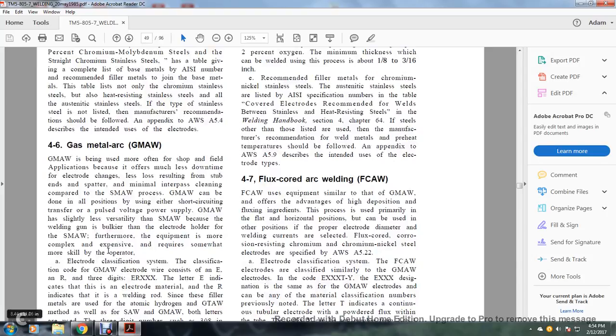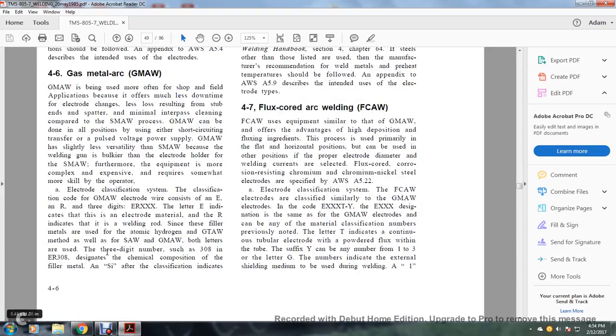Gas metal arc welding, 4.6. Gas metal arc welding is being used often in the shop and in the field, with less downtime for electrode changes, less loss from electrode stub ends, and minimum spatter and interpass cleaning compared with the shielded metal arc welding process. Gas metal arc welding can be done using short circuiting transfer or pulsed voltage power supply. It is slightly less versatile than shielded metal arc welding because the welding gun is bulkier than the electrode holder. Furthermore, the equipment is more complex and expensive, and the process requires more skill from the operator.